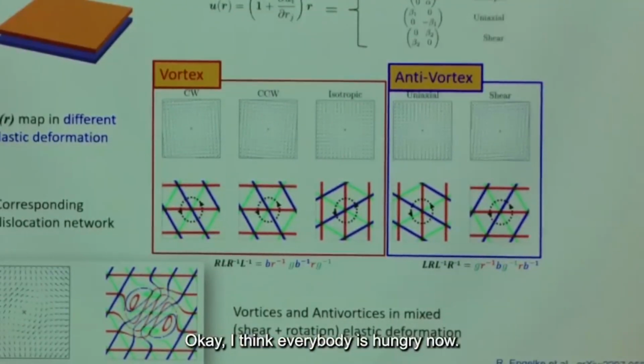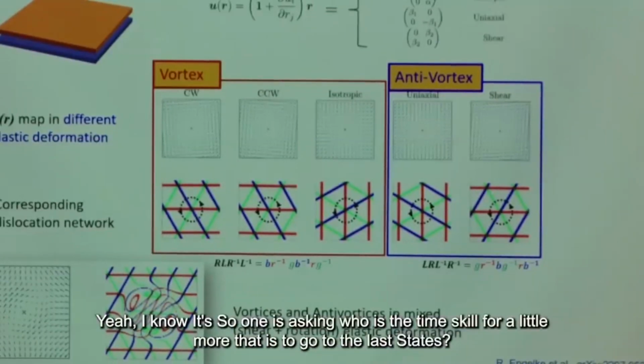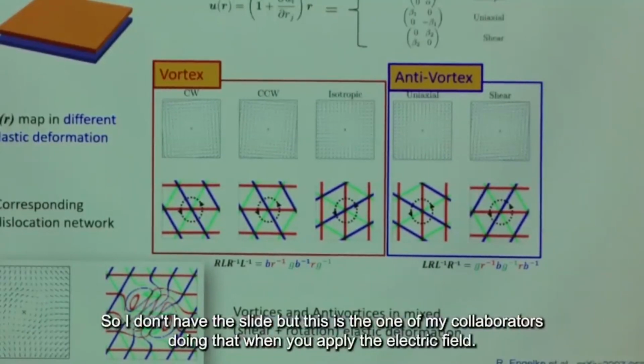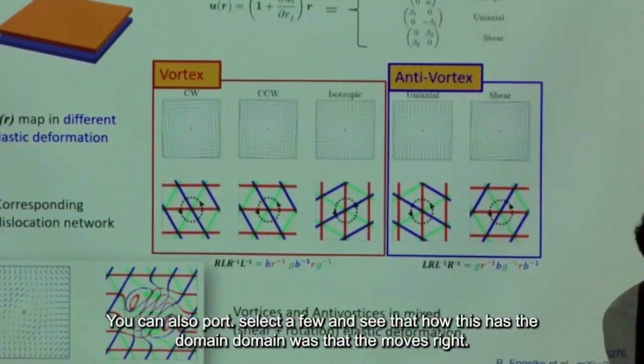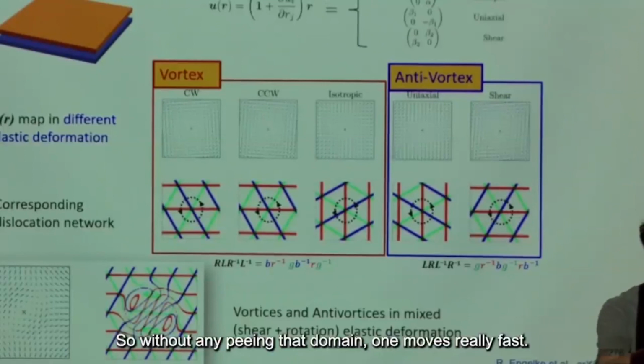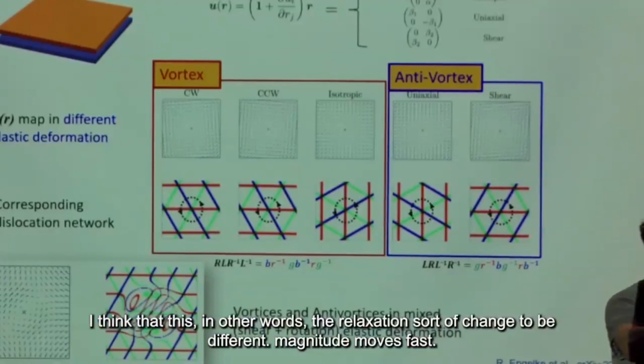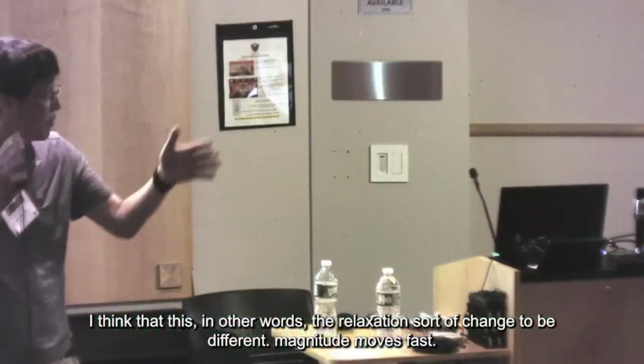Yes. So one question is, what is the time scale for the moiré lattice to go to the relaxed states? I don't have the slide, but this is an experiment that one of my collaborators is doing. When you apply an electric field, you can also pulse the electric field and see how the domain wall starts to move. Without any pinning, the domain wall moves really fast. In other words, the relaxation, the change with a different electric field, moves fast, probably close to the sound velocity.